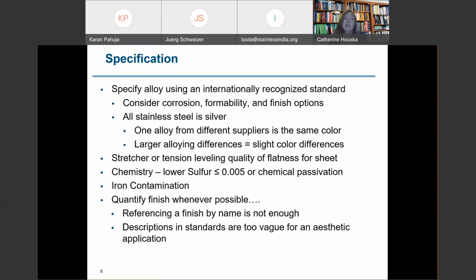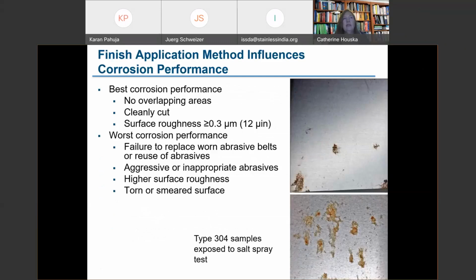The descriptions in the international standards are too vague for an aesthetic application, and that's part of what I'm going to talk about. I do want to point out that you could have 2 different number 4 finishes, and differences in how those are applied can mean a big difference in corrosion resistance. These pictures are both type 304 stainless steel exposed to exactly the same salt spray test. There is a lot more corrosion on one sample because the surface is rougher, it's not cleanly cut, and under a microscope, it's clearly torn. So finish application is important.